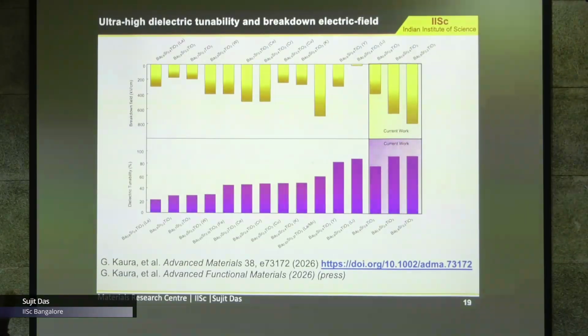Now, a summary of this work. We have seen very high dielectric tunability for this particular composition, BST20, where we see a mixture of tetragonal, orthorhombic and rhombohedral phases. If we compare with the existing literature for lead-free materials, we found that our case has a very high dielectric tunability as well as breakdown voltage.